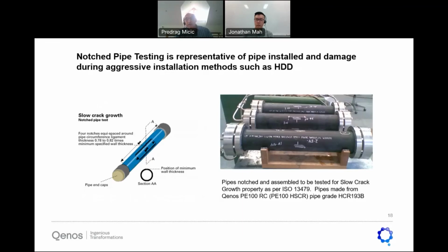So the notch pipe testing, as we said, in this case we're talking horizontal directional drilling. The presence of the notch is representative of pipe installed and damaged during an aggressive installation method, like HDD. And for PE compounds, we do have a test for that. Resistance to slow crack growth is measured by the notch pipe test according to ISO 13479. The test is done on SDR11 pipes, notched by standardized procedures up to 20% of the pipe wall thickness, and then the pipe is pressurized to 920 kPa, which is about the right stress that they see in the field, at 80 degrees, and the time to brittle failure is recorded.